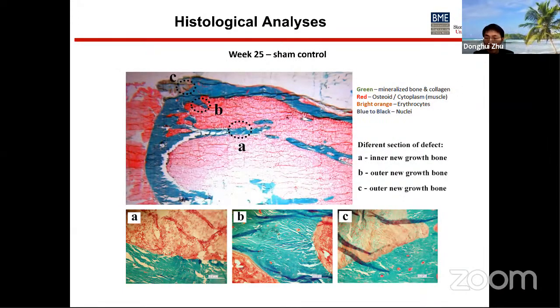Here is the sham control. Again, the two layers of bone still exist, with the outer layer thicker than the inner layer. Vascularization is also observed around both the inner and outer layer, with some mixture of mineralized bone and osteoid remaining around the outer layer.